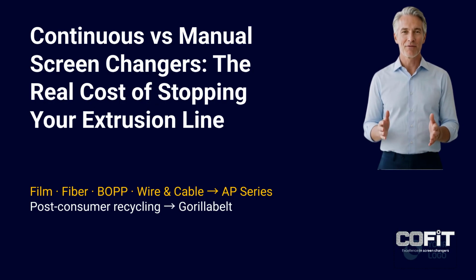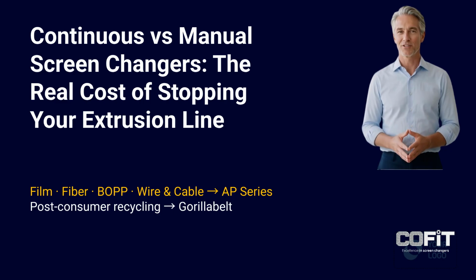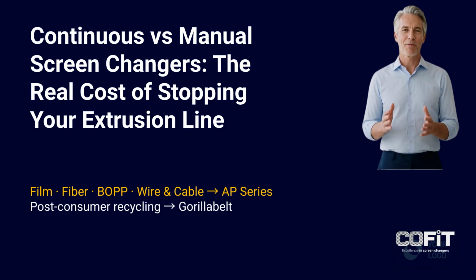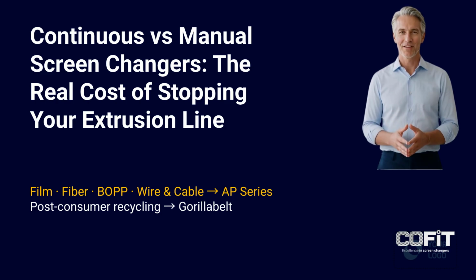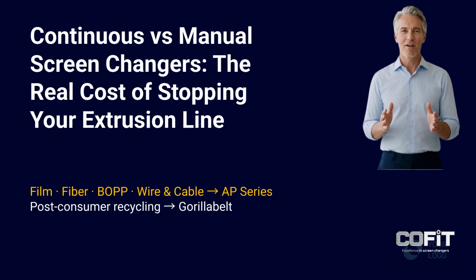For film, fiber, BOPP, extrusion coating, wire and cable, and compounding on clean or low contamination feedstock, a continuous dual cartridge screen changer provides the pressure stability and gel removal capability these applications require. For post-consumer and post-industrial recycling, where contamination levels of 3 to 10% make conventional screen changers impractical, a continuous belt screen changer is the appropriate technology. For lines with very low change frequency and low sensitivity products, pipe, profile, simple compounding on virgin polymer, manual or hydraulic equipment may be economically sufficient.